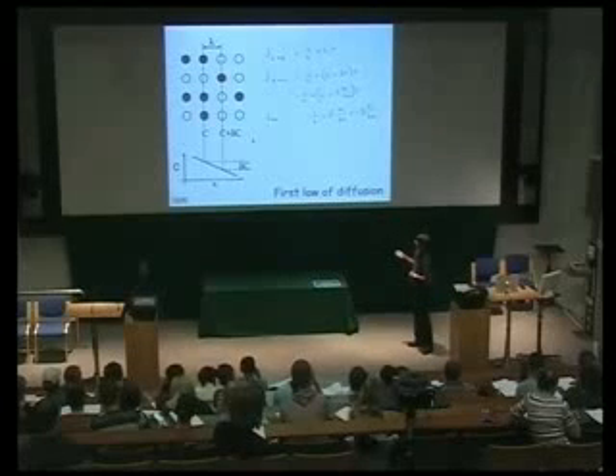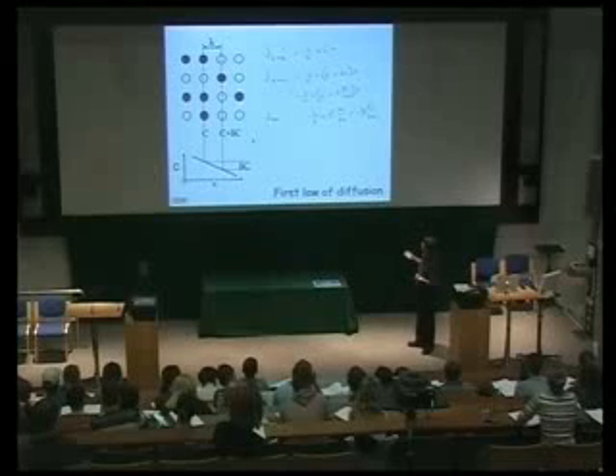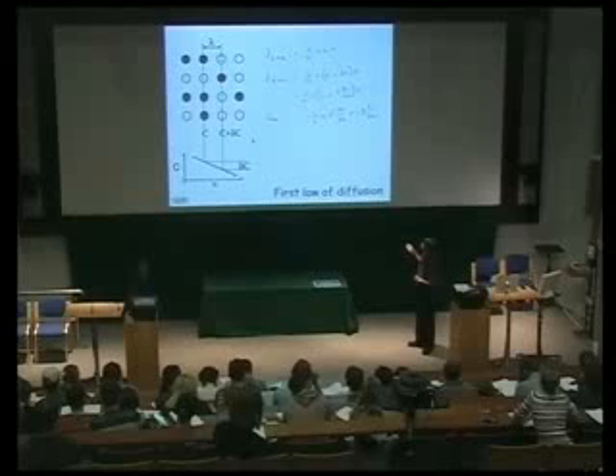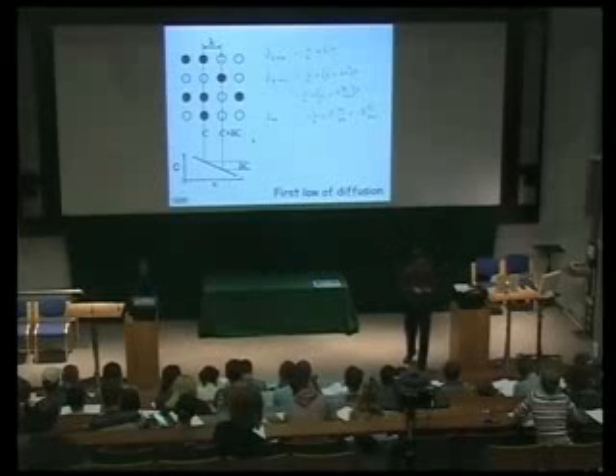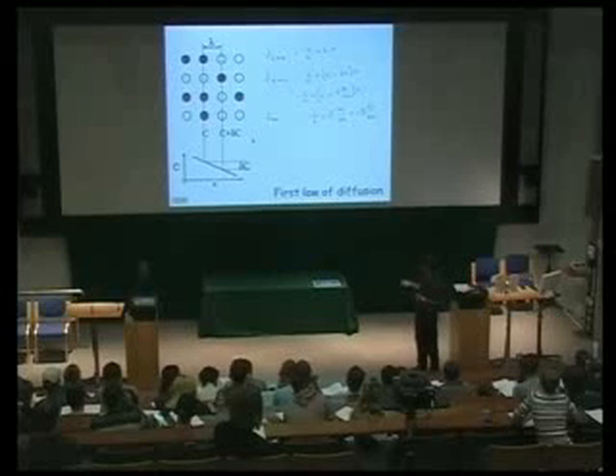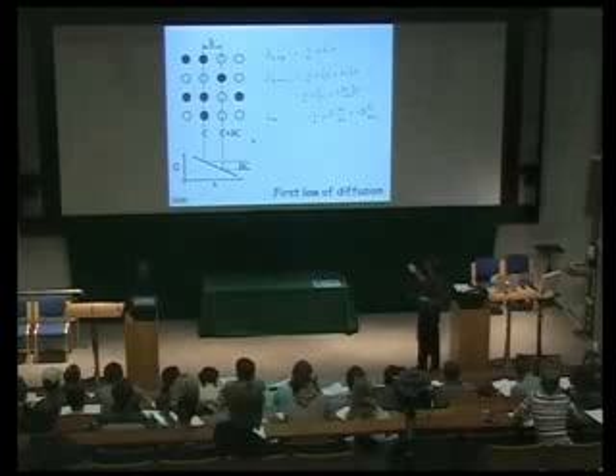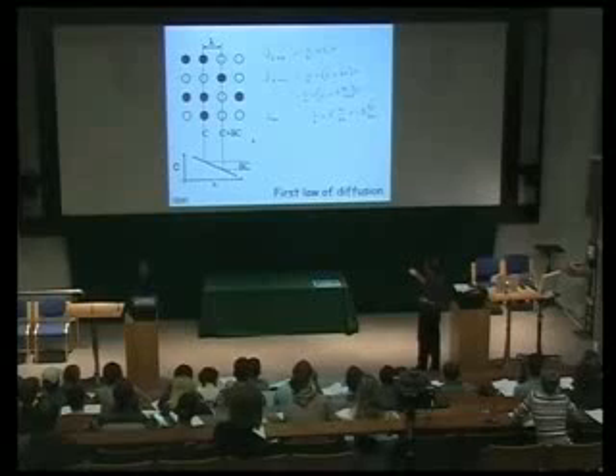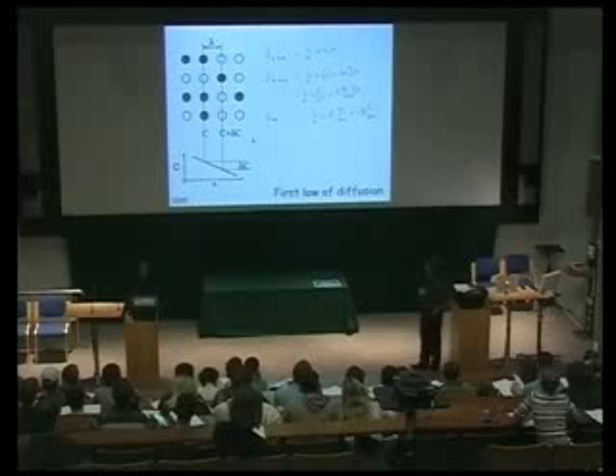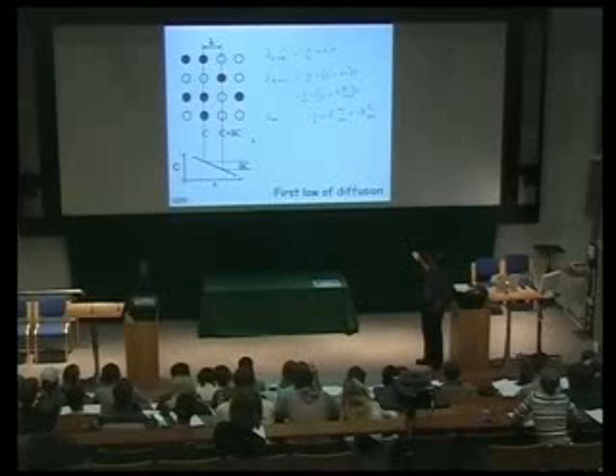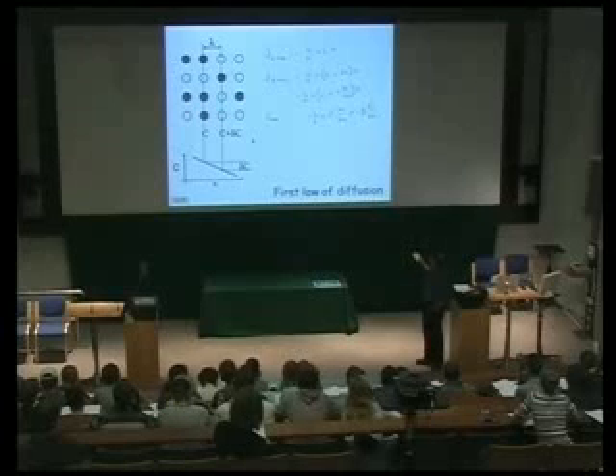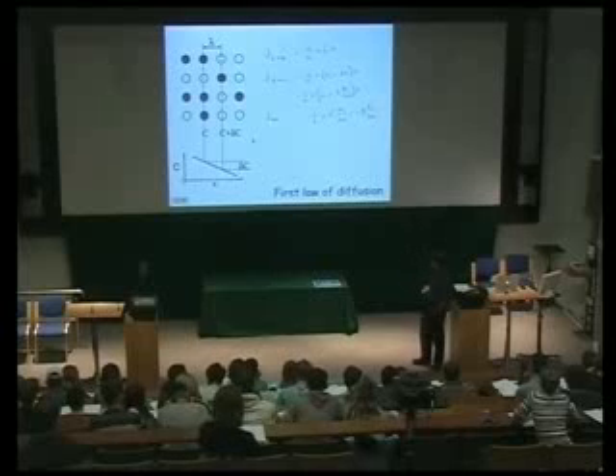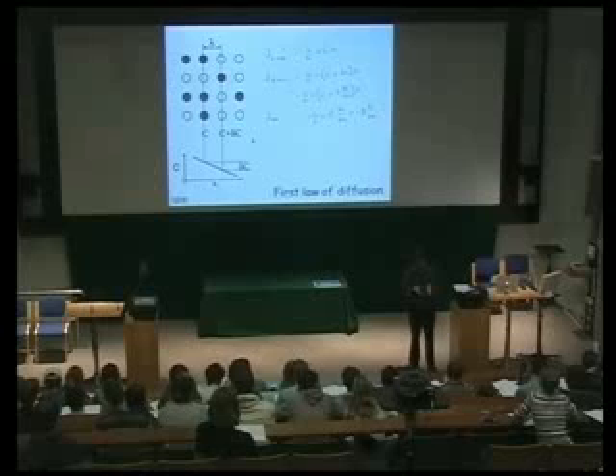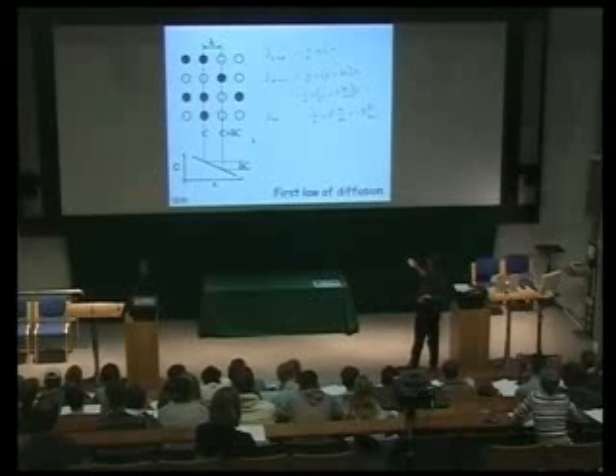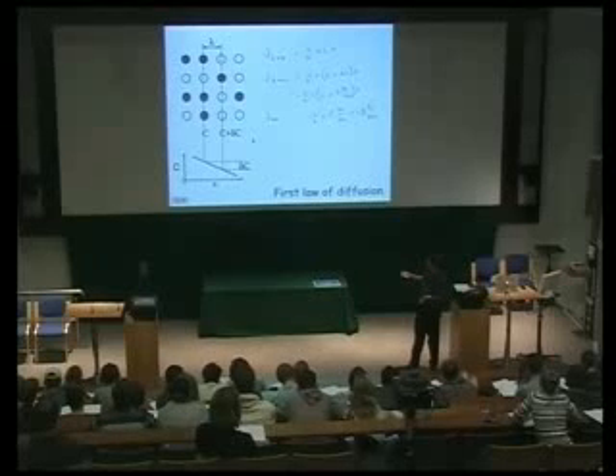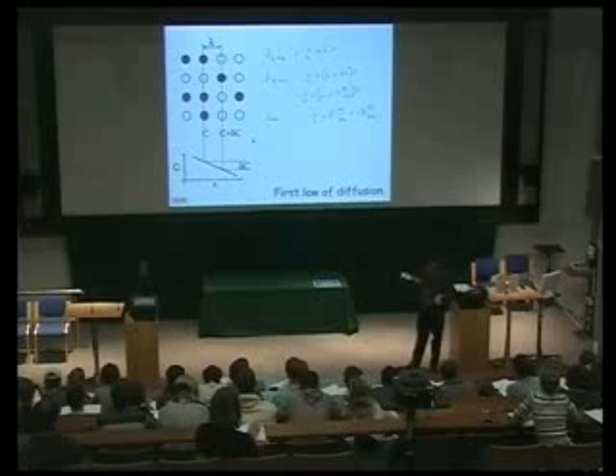Similarly, if I now look at jumps in the reverse direction, the concentration now is C plus delta C. So this equation is very similar to this, except now the concentration has changed. So if I want the net flux, which is defined along the direction x, then I simply take the difference between these 2 equations, and we get this relationship. Now, what I've done over here is I've changed delta C into lambda times dc by dx. Okay? So lambda is effectively the jump distance, and this is the gradient. If I multiply the gradient by the jump distance, I get the change in concentration. So here's the gradient. If I multiply it by the jump distance, then I get delta C, right?